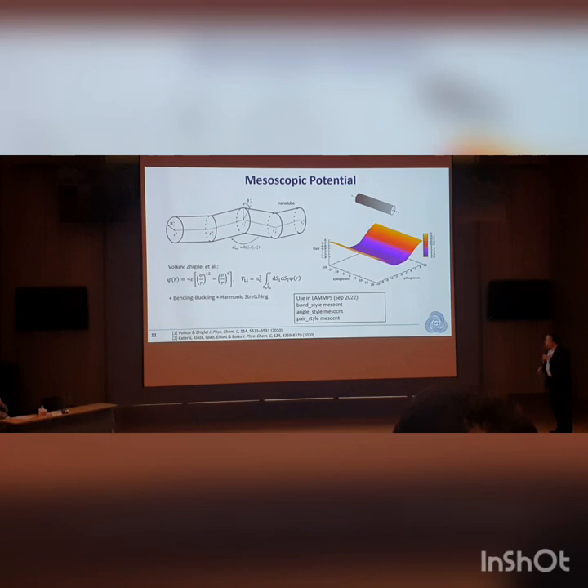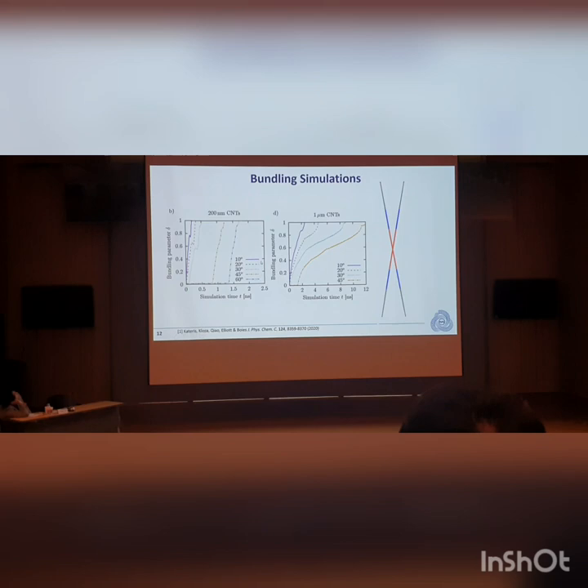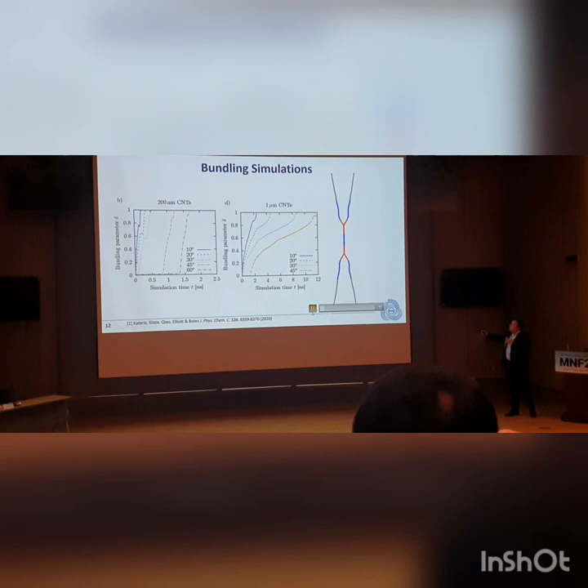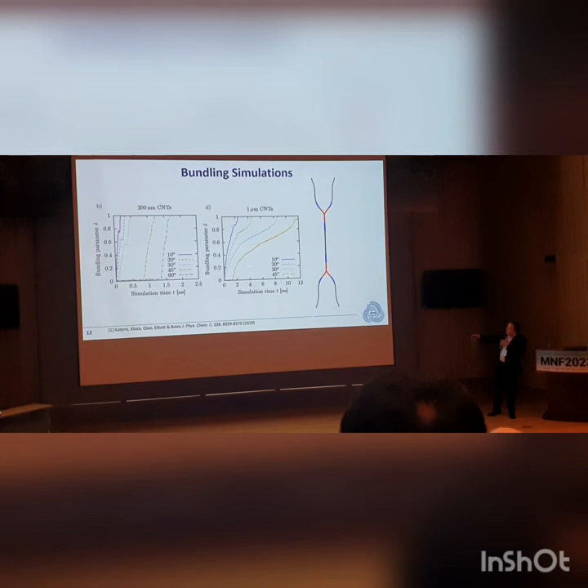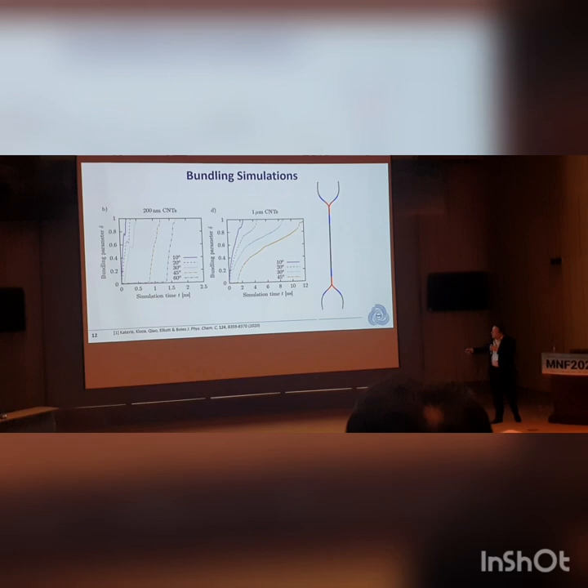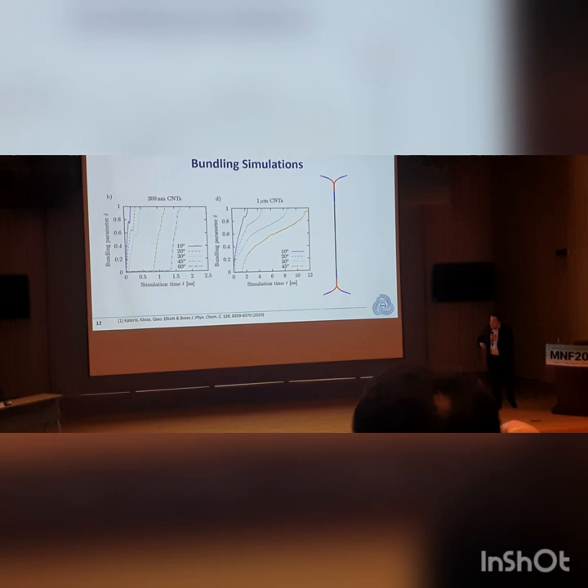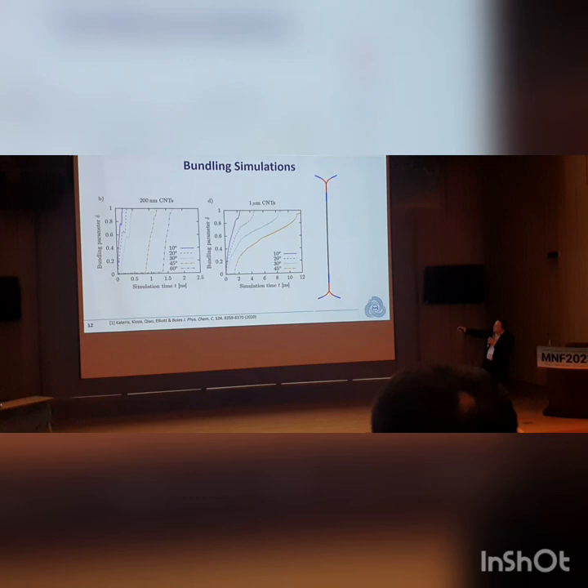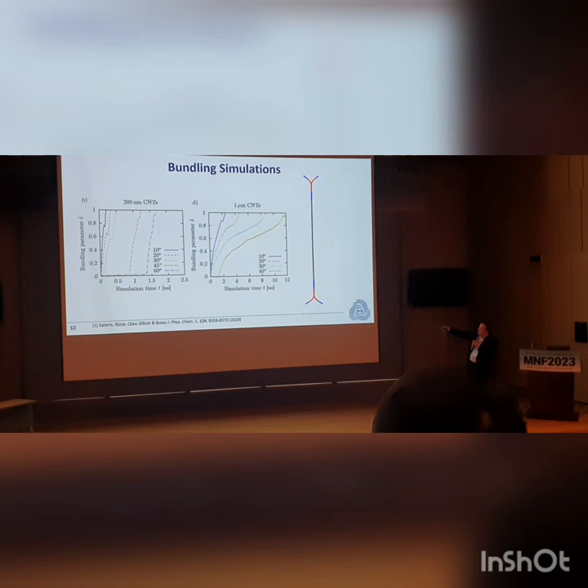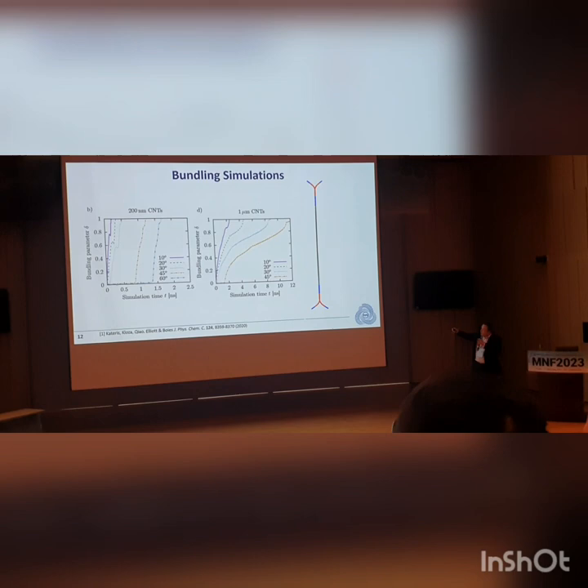As Adam showed, the simulations lead to bundle formation. Looking at a couple of tubes crossed at some initial angle, as time goes on they zip together. There's a critical angle at which they need to cross before zipping occurs. The model is also adaptive: orange regions are fine-grained, blue regions are slightly more coarse-grained, and far from junctions the coarse-graining increases significantly, speeding up simulations. We measure the bundling parameter — the amount of tube in contact with the other tube as a function of time.